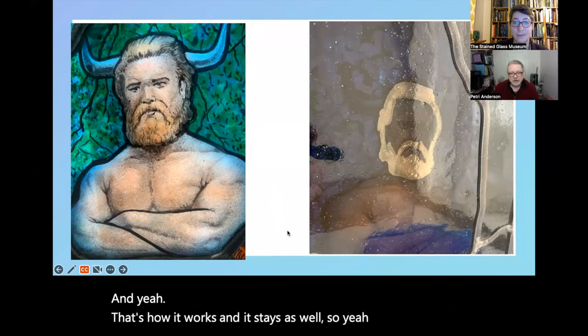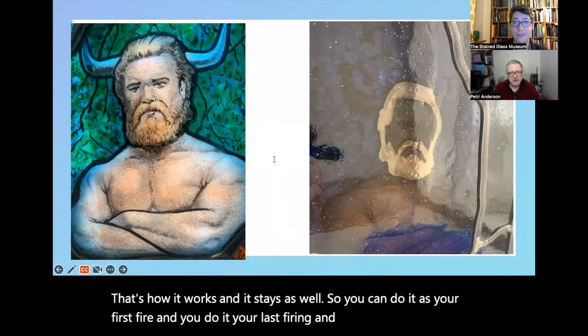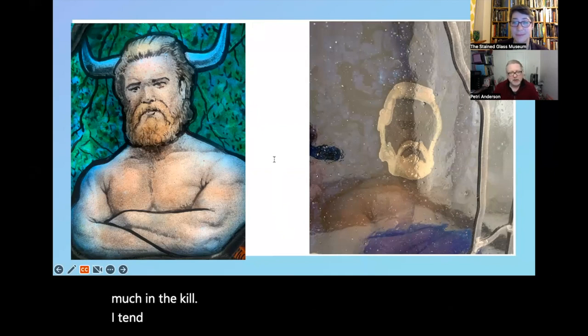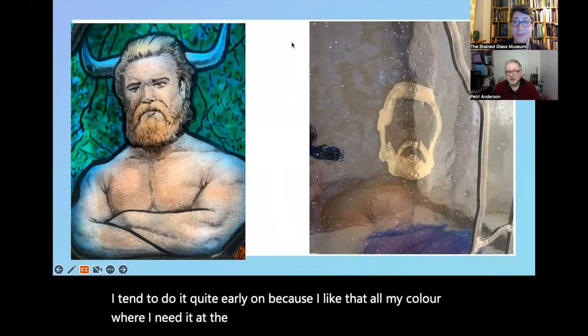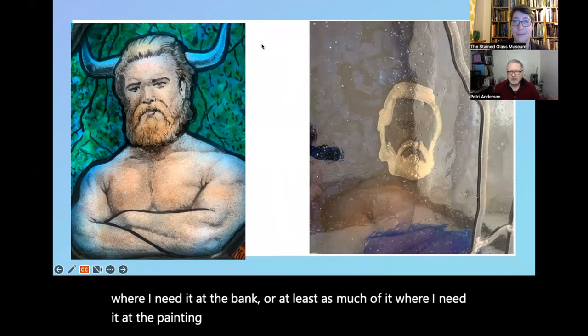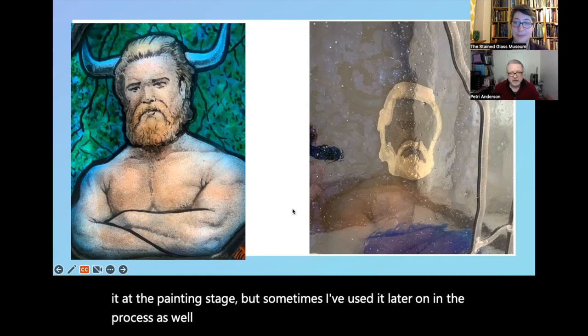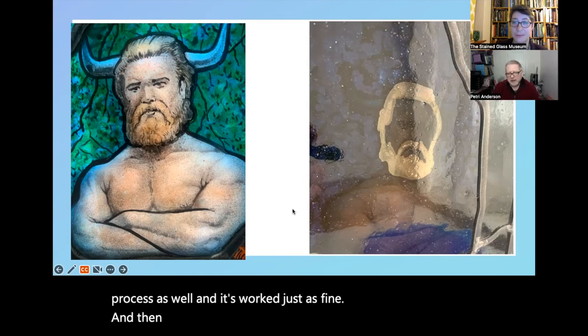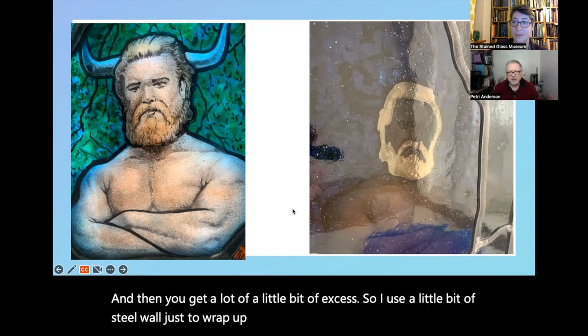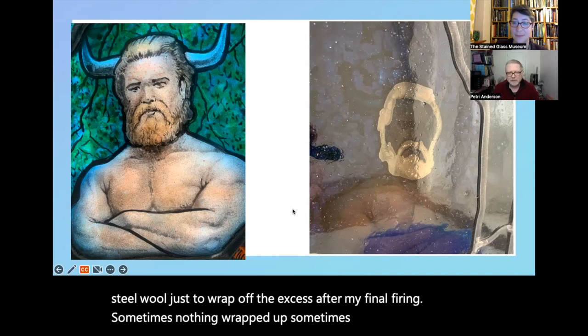So you can do it as your first firing, you can do it as your last firing, and it won't change too much in the kiln. I tend to do it quite early on because I like to have all my colour where I need it at the paint stage, or at least as much of it as possible. But sometimes I've used it later on in the process as well, and it's worked just as fine. And then you get a little bit of excess, so I use a little bit of steel wool just to rub off the excess after my final firing. Sometimes nothing rubs off, sometimes there's a little bit to rub off. So that's how I use it.